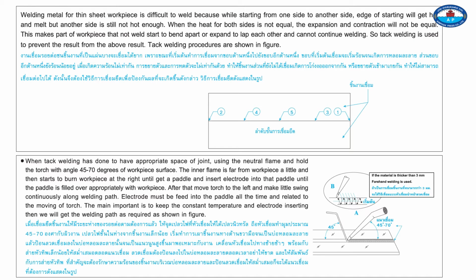When tack welding has been done to have an appropriate space at the joint, use a neutral flame and hold the torch at an angle of 45 to 70 degrees to the workpiece surface. The inner flame is kept a little away from the workpiece, then start to burn the workpiece at the right until you get a puddle, and insert the electrode into that puddle until the puddle is filled over appropriately with the workpiece. After that, move the torch to the left and make a little swing continuously along the welding path.